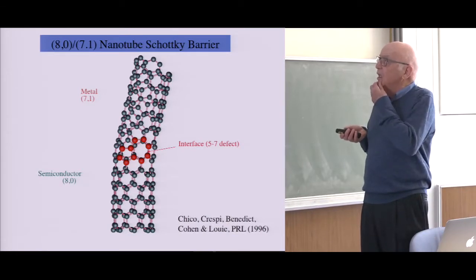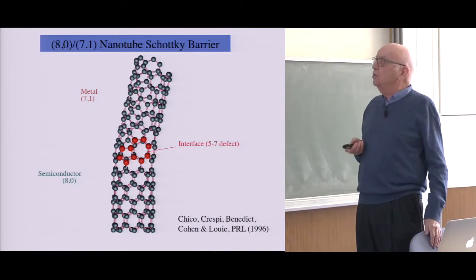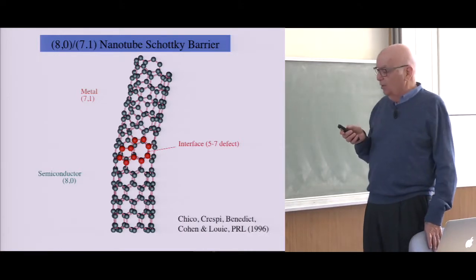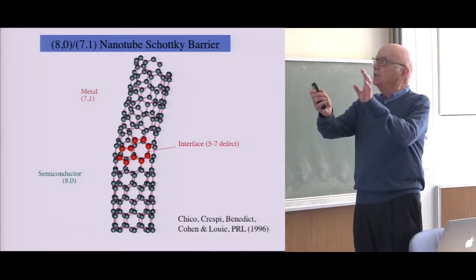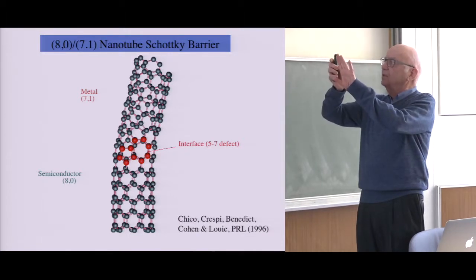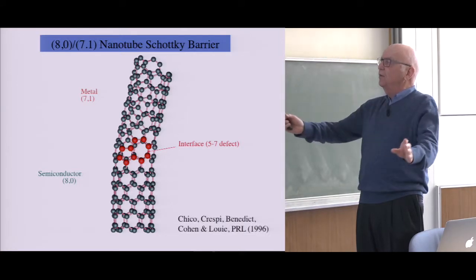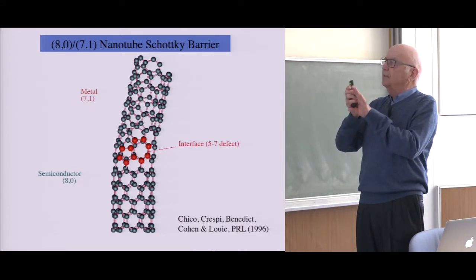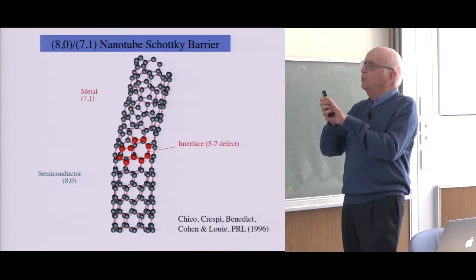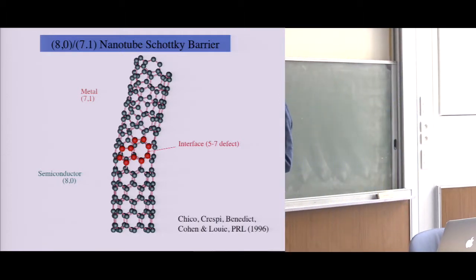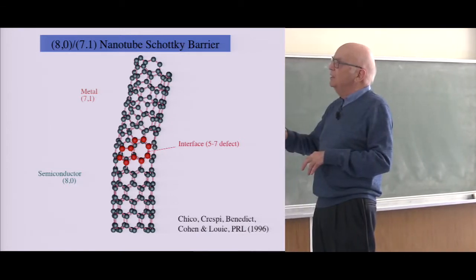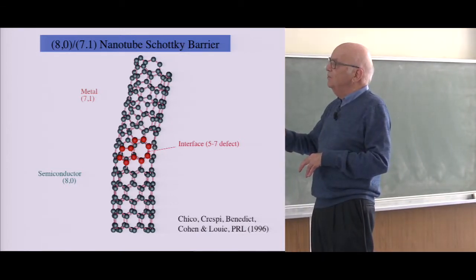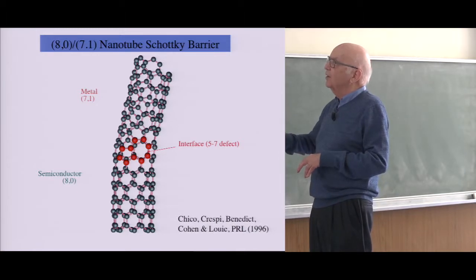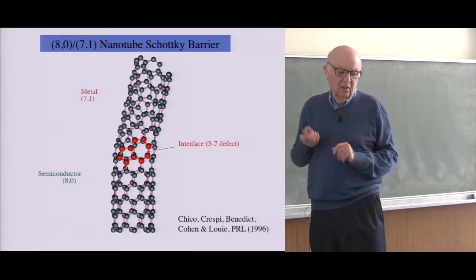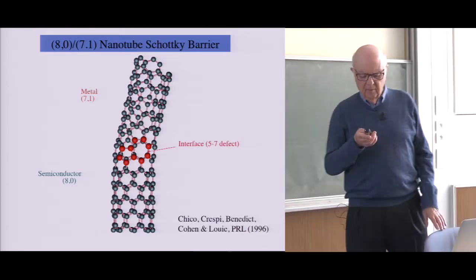Now, if you roll graphene into tubes, there are a lot of experiments you can do. If you roll graphene around so that you go 7 hexagons and move it up 1, that's a metal. If you go around 8 and don't move it up, that's a semiconductor. And if you put them together, and nature does this for you, you can get a defect with 5-fold and 7-fold rings, and this is a Schottky barrier. And these were predicted on the computer, and they've been found.